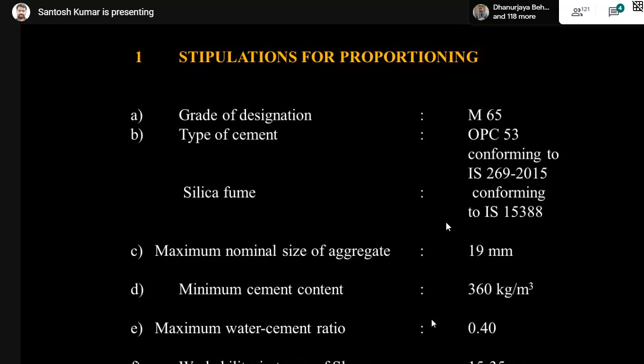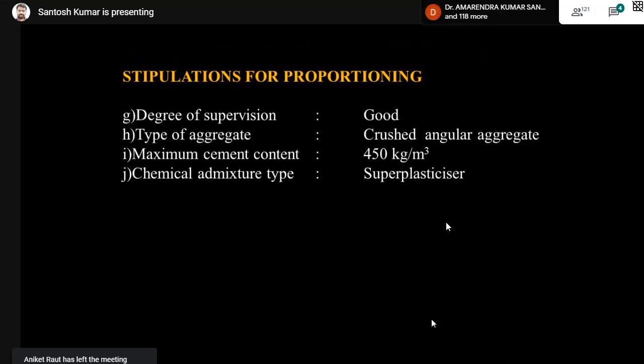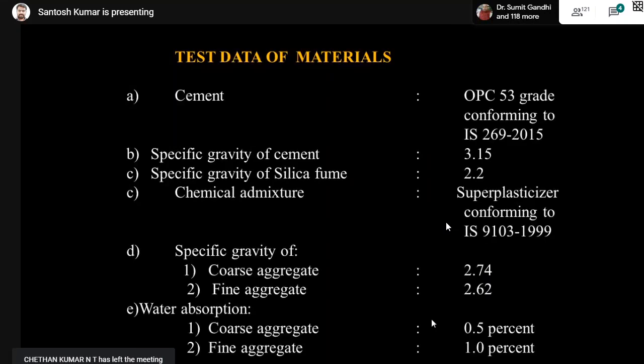Minimum cement content, we all know, is 360. Maximum water cement ratio is 0.4, and workability requirement is 15 to 35 mm. The degree of supervision is good, and the type of aggregate is crushed angular aggregate. Maximum cement content is 450 kg per cubic meter, and for chemical admixture we are using superplasticizer.